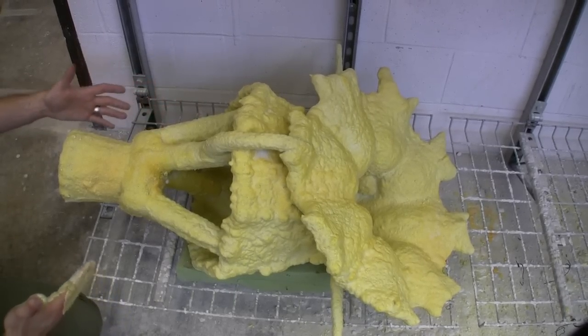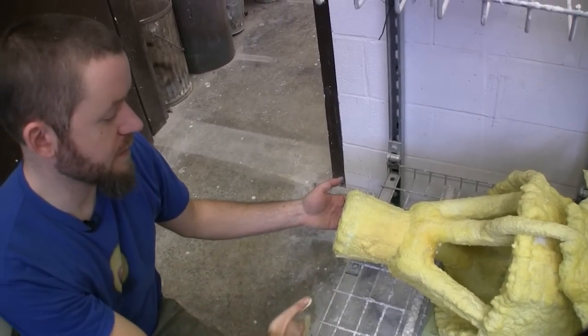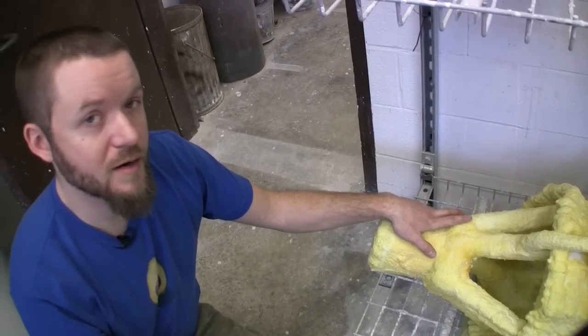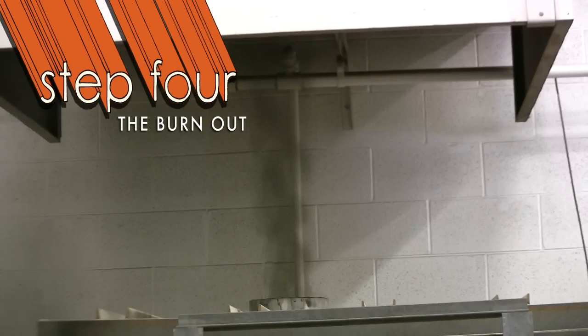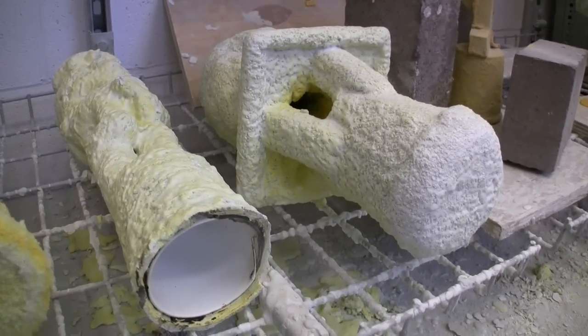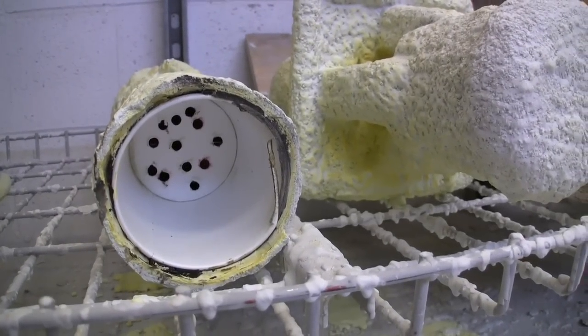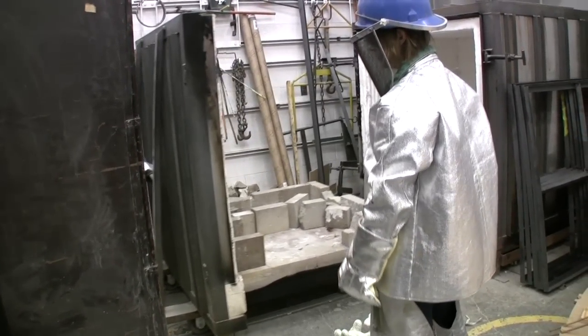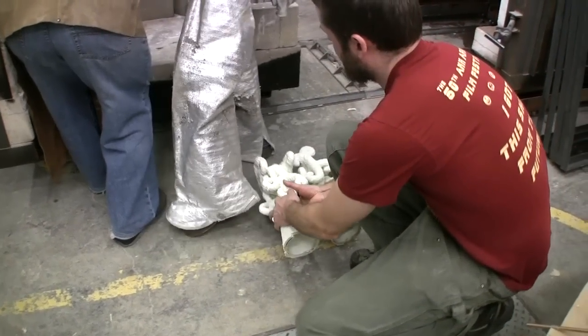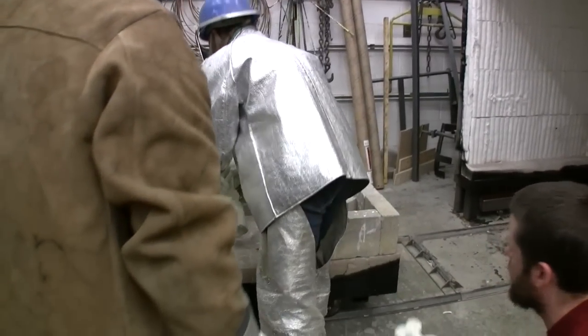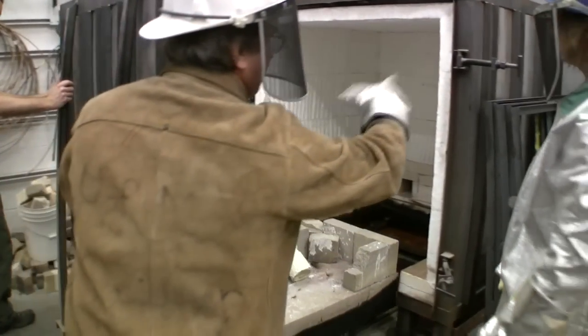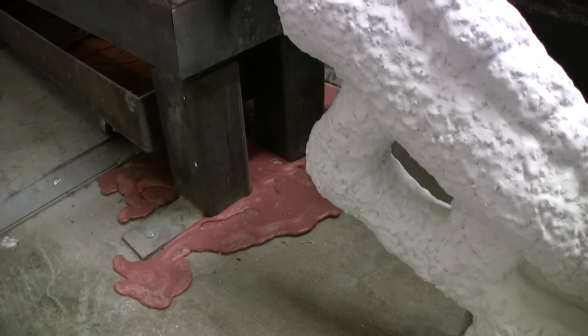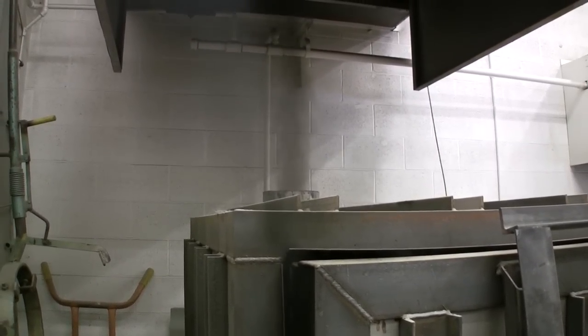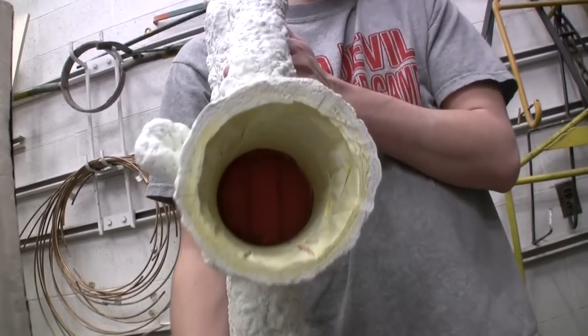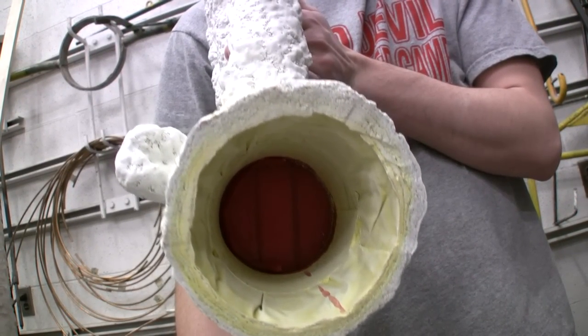After that, what happens is we can open up this cup. We literally just cut this off, and then we do a burnout. So the burnout is the process of cutting the cup open on your ceramic mold so that the wax has a place to flow out of. Then preheating a kiln to 1,150 degrees Fahrenheit, loading the piece into the kiln when the kiln's already hot, and doing what's called a flash burn. So it's just like a flood of wax comes pouring out of your piece. Then what you have is a hollow ceramic mold, and that hollow, you have to imagine, is a negative impression of your original sculpture. And now, Grasshopper, you're ready to pour bronze.